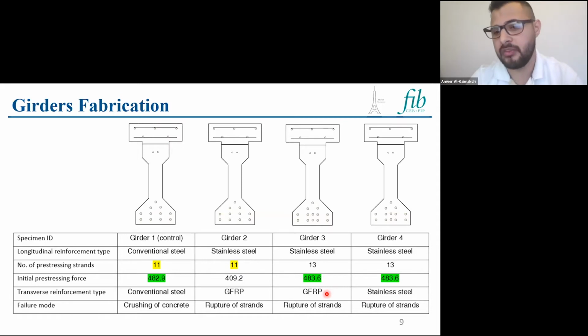Girder 3 had GFRP rebars. GFRP is glass fiber reinforced polymer. They are corrosion-free rebars. Stainless steel rebars are corrosion-resistant rebars. And then for girder 2, the shear reinforcement was GFRP as well. We wanted to have a girder that is as corrosion resistant as possible. And then for the control girder, we had conventional steel rebars.